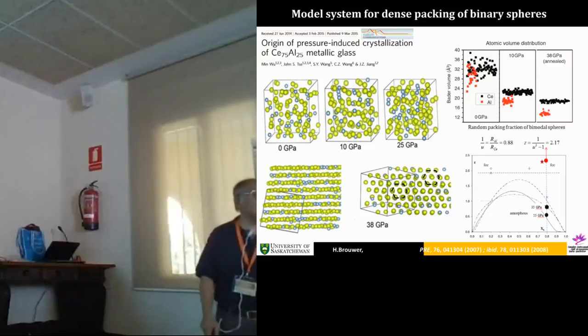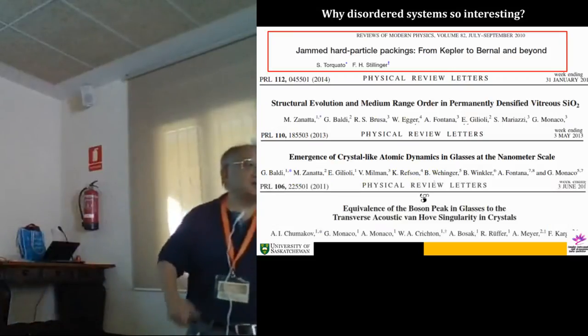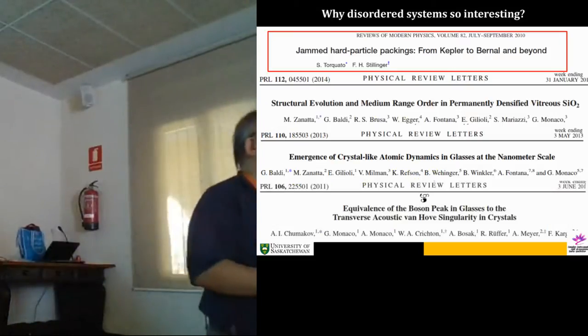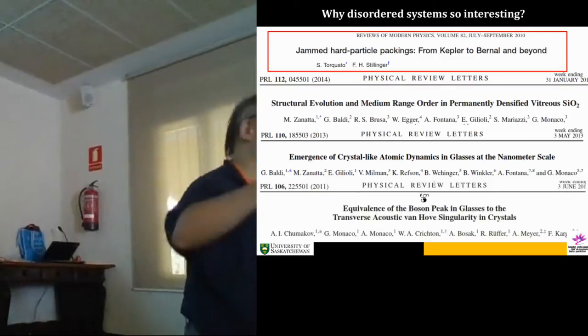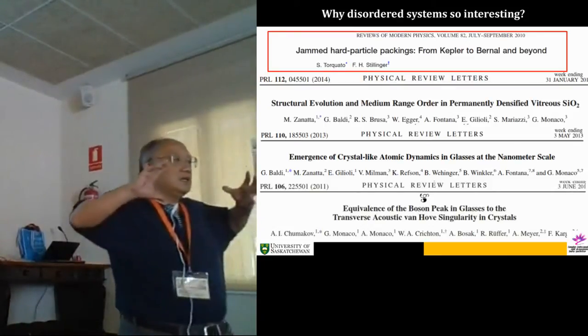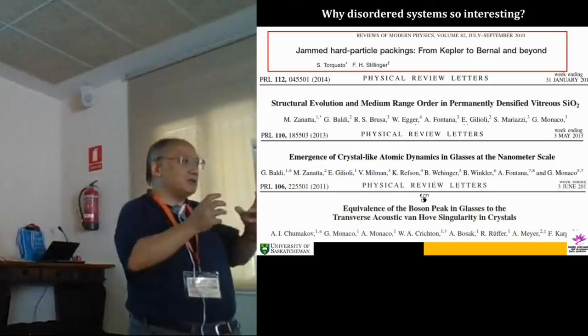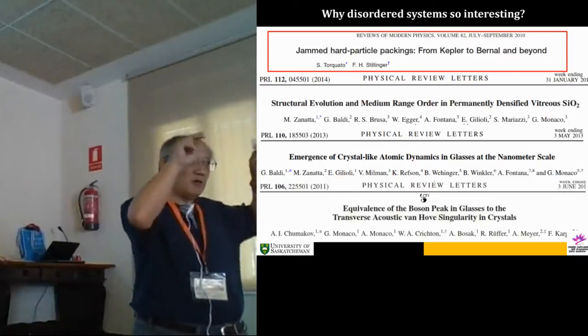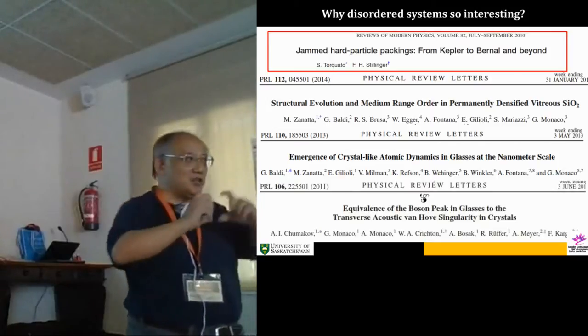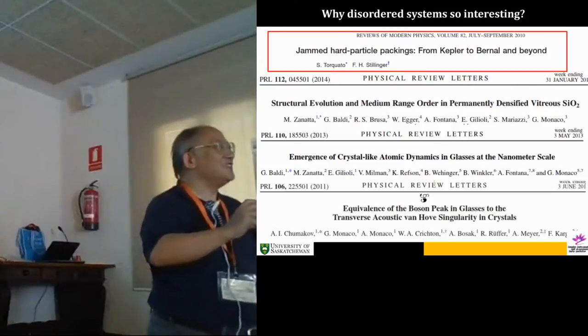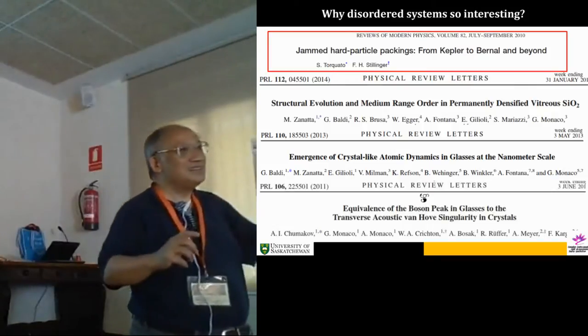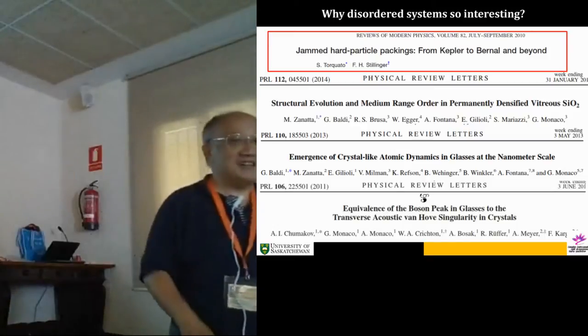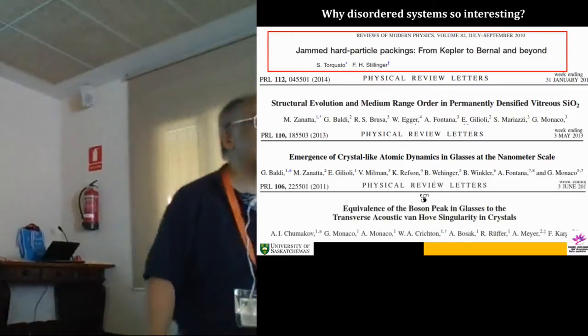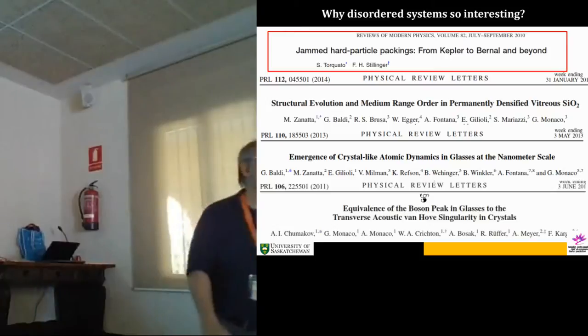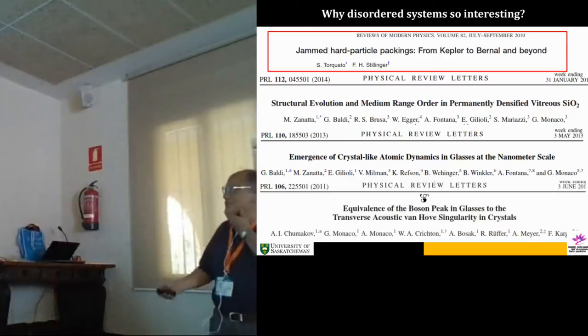It turned out that one thing most people forgot when you compress a binary glass, a binary system, any binary system. When you compress it, the electron got rearranged. But the size, so-called quote-unquote the size of the two, the ratio of them, is not constant. You press sodium chloride, it's not exactly the same in ground state. And people forgot about it. After you understand it, it's so easy to understand why it crystallized. I don't tell you the story.